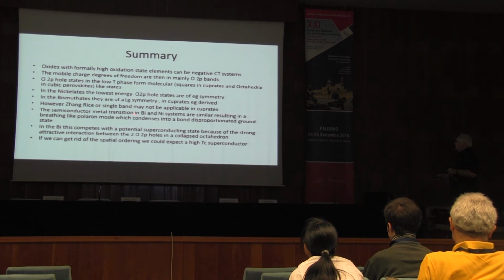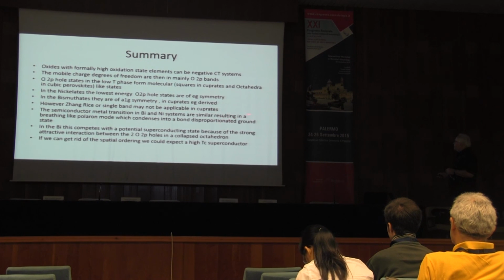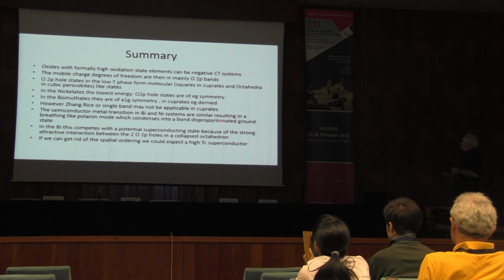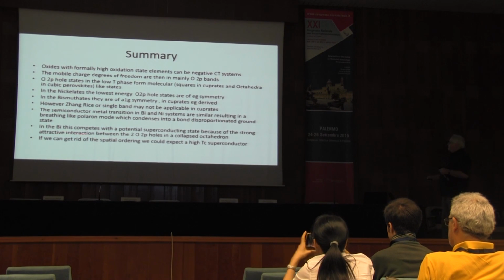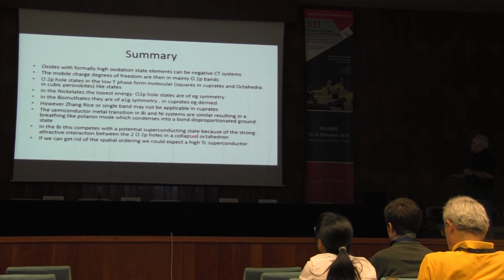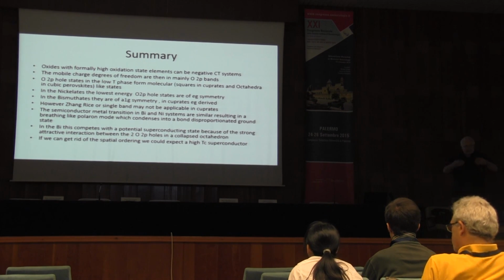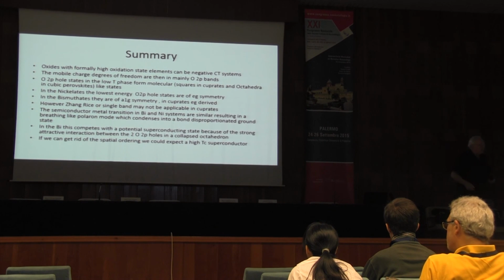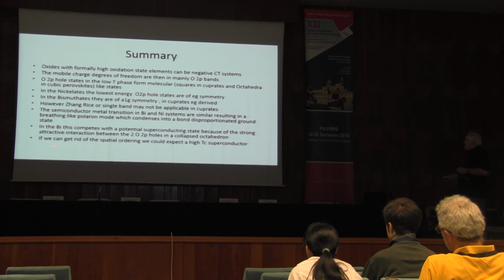The semiconductor-metal transition in bismuth and nickel systems are similar, resulting in a breathing-like polaron mode which condenses into a bond disproportionated ground state. In the bismuth, this competes with a potential superconducting state because of the strong attractive interaction between the two O2p holes in the collapsed octahedron. Attractive because of the common coupling to the bismuth. If we can get rid of the spatial ordering, we should expect to get high-Tc superconductors.